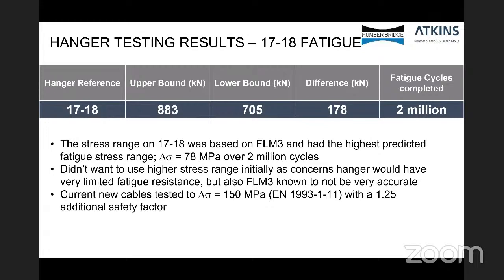So this was the fatigue testing carried out. The upper bound load was 883 kilonewtons with a lower bound of 705, a 178 kilonewton difference. The fatigue cycles were over 2 million cycles. Now the stress range on 1718 was based on the FLM3, which is one of the Eurocode loading parameters, and that's a fatigue loading vehicle crossing over the bridge. It had the highest predicted fatigue stress of 78 megapascals over 2 million cycles.